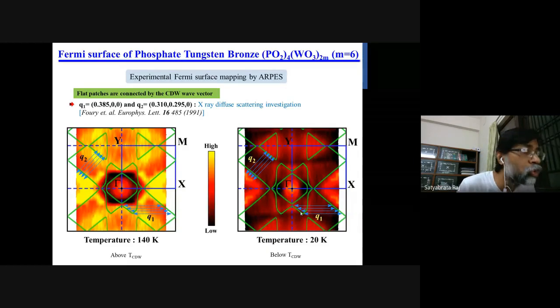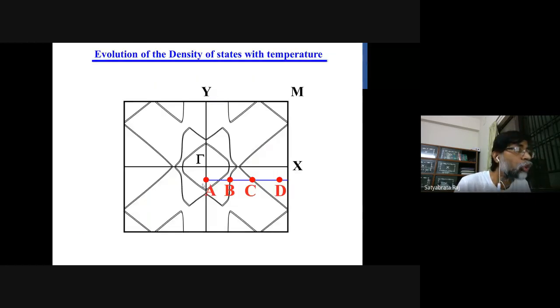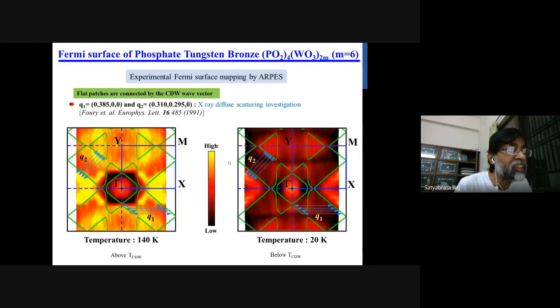To understand how much density of states is removed, we have taken a cut in this direction, because the small Fermi surface at gamma is not taking part in any nesting. Only these straight patches are taking part in the nesting of the Fermi surface. This Fermi surface is intact at low temperature and high temperature.